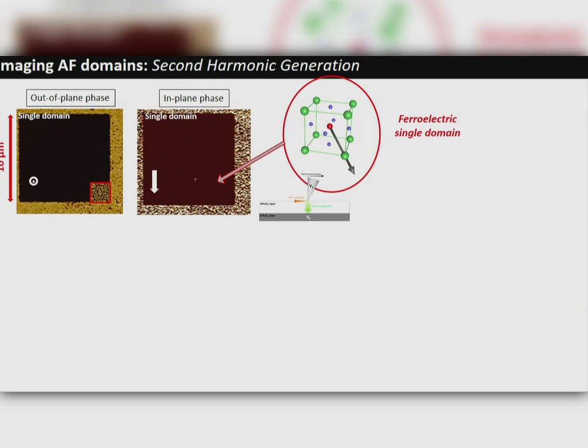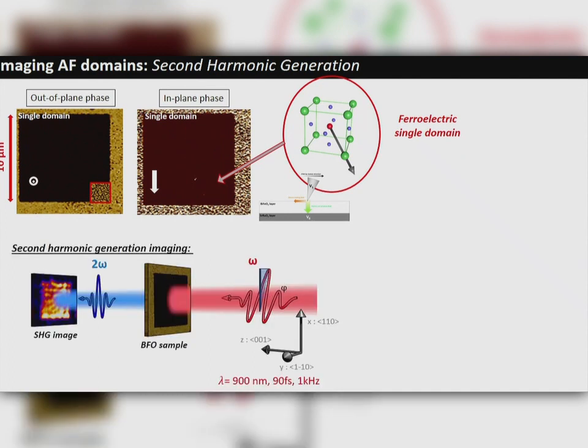From 4 to 1, and basically, you reduce the problem of the S domain for the antiferromagnetic domain from 12 to 3. So basically, we are able to write this single domain. So we do these experiments. So basically, we do a wide field experiment. So we shine the light on the sample, and then we collect the light in a CCD camera. So I spare you all the technical details.